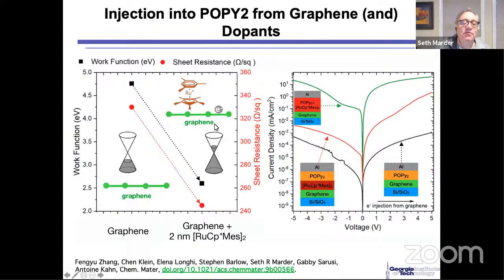By the way, I was wrong about not including the slide. So here is the slide where Antoine vacuum dopes the graphene, and you can see he takes the work function down to about 2.5 with the graphene, and he knocks the sheet resistance down. There's a molecule that I'll show later that's pretty hard to inject into. He shows that in the absence of the dopant, it's pretty hard to drive current in. If you put a very thin layer of dopant between the graphene and this POPY2, which I'll show you a couple of slides later, they get a 2 to 3 orders of magnitude increase in the current in the forward direction.